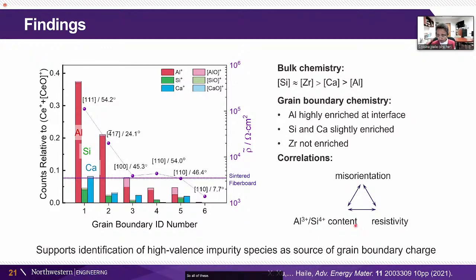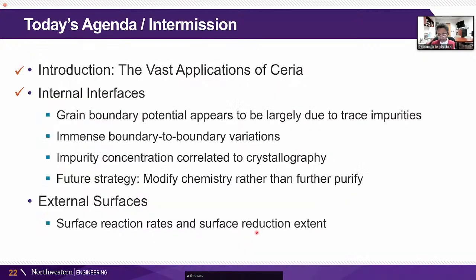So all of these things are correlated, and now we can understand what the origin of the space charge effect is. But really it is about these high valence impurity species that end up at interfaces which have a high crystallographic misalignment associated with them. So that is our story now on the internal interfaces, that we have these grain boundary potentials, which we've confirmed that they really are there, which had not been done before in the literature. There was a lot of circumstantial conclusion that they occur. We see that it's largely due to trace impurities.